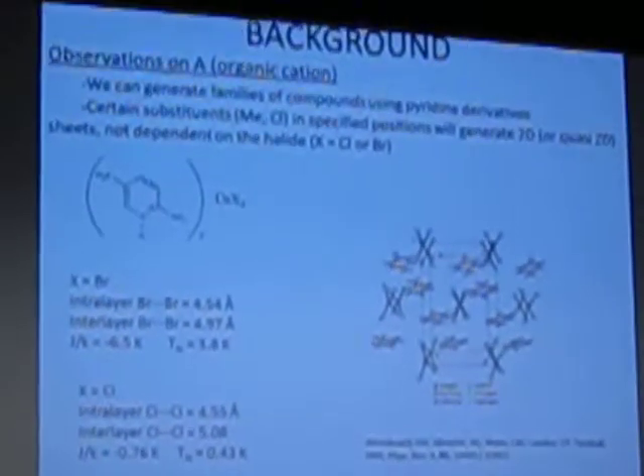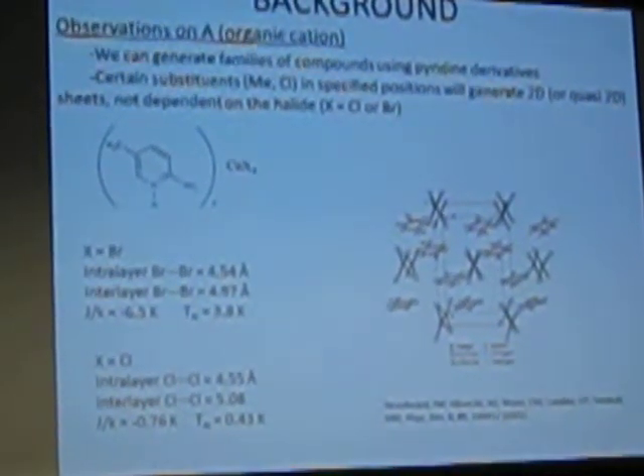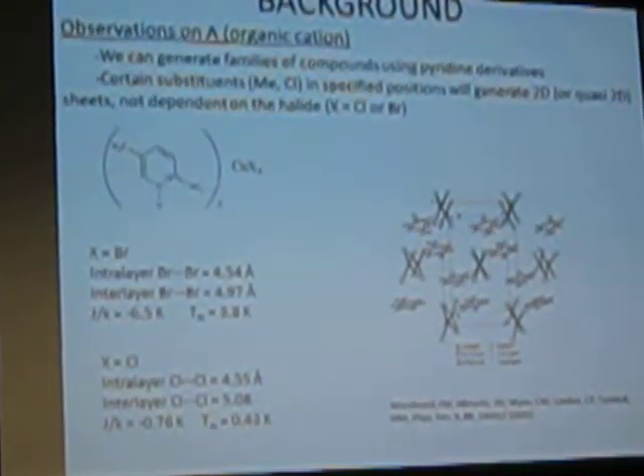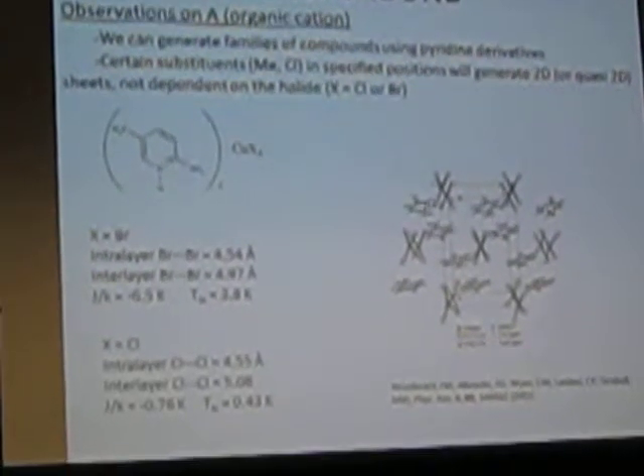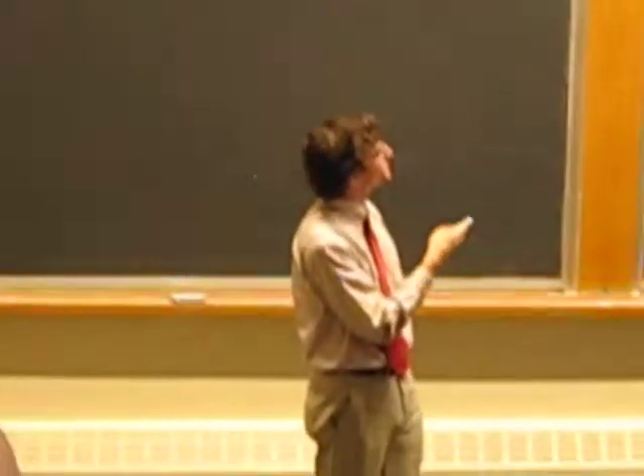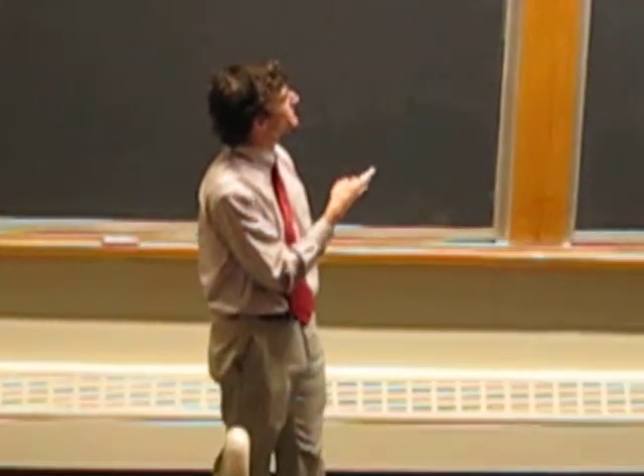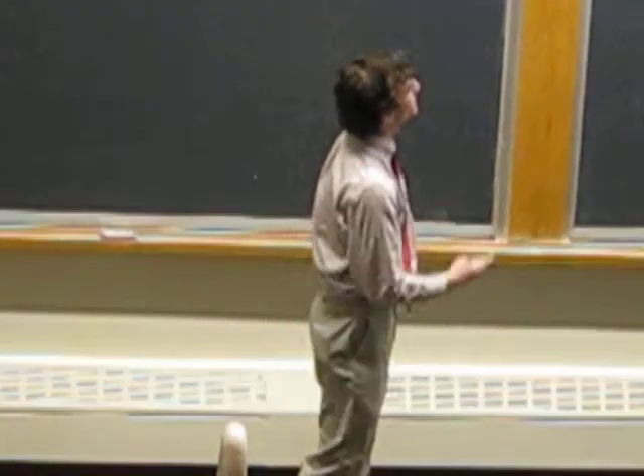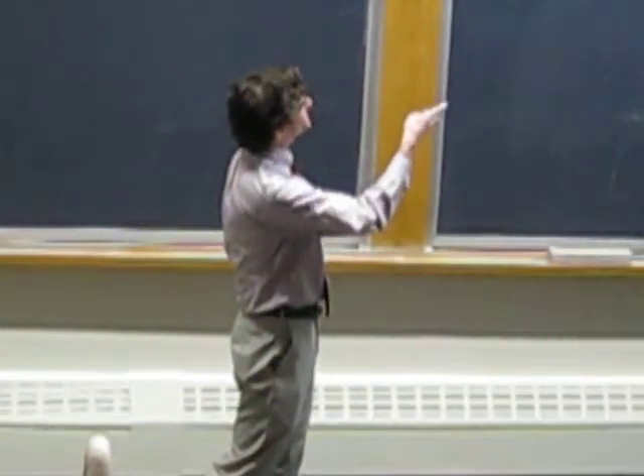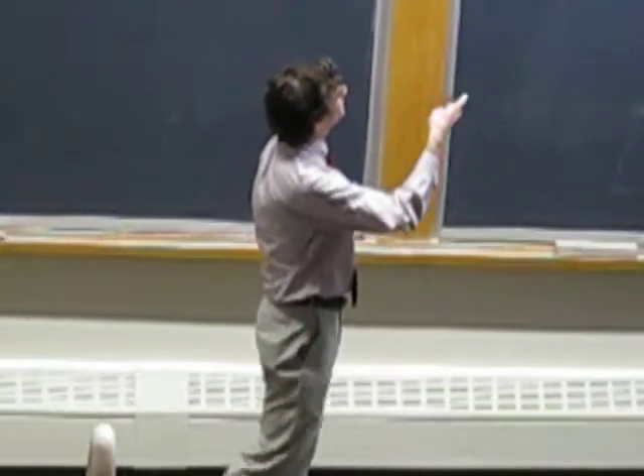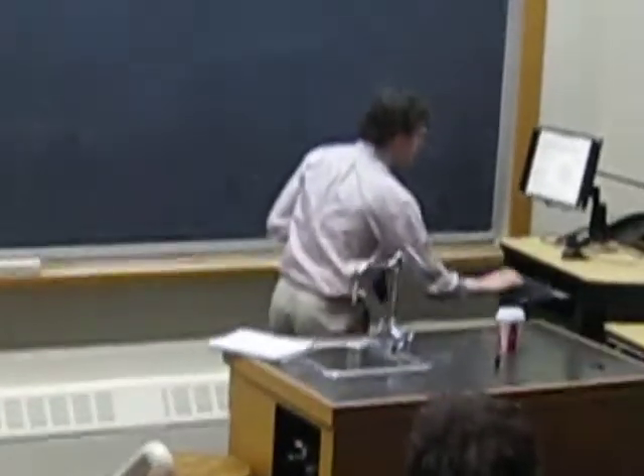When you switch to the chloride, the interactions are a little bit weaker, and also the 3D transition temperature is a little bit lower. This is a function of the distances; they haven't really changed between the size of the square, but the distances between the layers have increased a little bit, so that also has decreased the temperature of the transition. This is just a crystallographic representation of the chloride. The chloride and the methyl compounds look exactly the same.